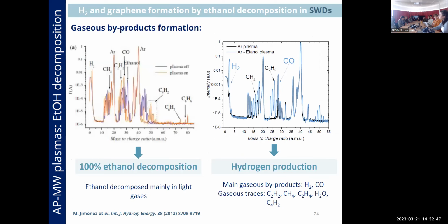But to make sure of the percentage of decomposition of ethanol, we use mass spectrometry. In this first graph, what we are comparing is a mixture of argon and ethanol gas with no plasma. This is what we call plasma off. There is no plasma at all. However, the orange line represents the mass spectrum of the same gas composition, but with the plasma on. So we are detecting the gases coming out of the plasma. We can observe that after switching on the plasma, the baseline of ethanol, which is located at mass-to-charge ratio 31, completely drops. So it allows us to conclude that the ethanol is completely decomposed in our plasma.